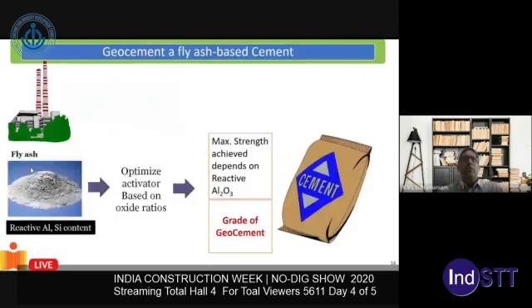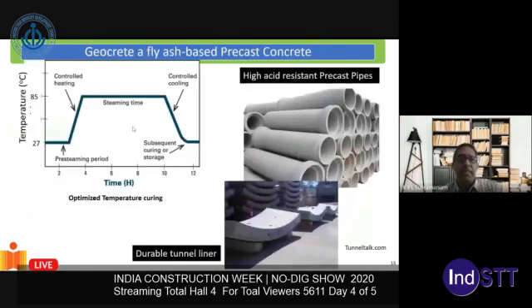Now, from there, we are able to collect fly ash from different thermal power plants and optimize the activator for this, and produce cements which give us consistent strength and consistent properties. This is done following the characterization of the fly ash obtained from these thermal power plants. And this cement would produce a geopolymer, which gives us consistently high strength and high durability. This is fly ash that's being produced across the country, and mostly in rural settings.